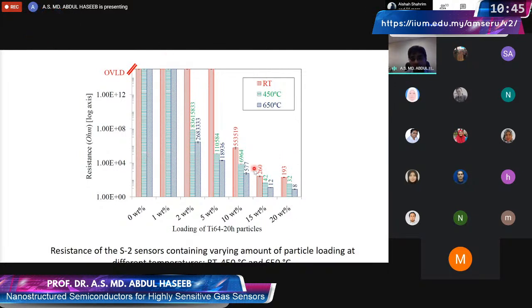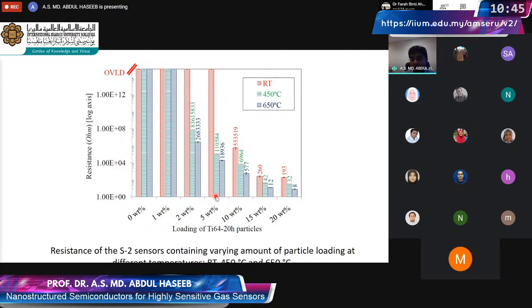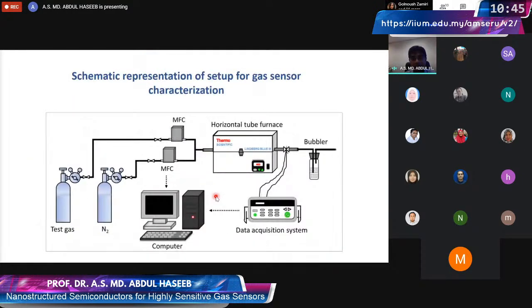On the other hand, if the particle loading is very high, the resistance is very low, and they are not sensitive to gases. So this is the range of about, let's say, 2 to 5% of loading, where we can optimize the sensor, and the sensor performs satisfactorily. So we use this, and then we prepared our sensors.